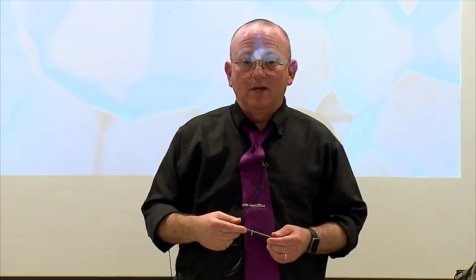That's what I'm saying. Now, imagine a system where there is no segregation, no equilibrium segregation. You have a dopant in solution, and it doesn't reduce the grain boundary energy, so it won't go there. And you go down to the length scales that you're talking about. Well, then we're talking about another thermodynamic parameter, which of course can shift the line of coexistence. And so the answer is obviously yes. But there are two different phenomena. And I address that because I've had problems of late with people assigning excess at boundaries as being part of the solute. And it's, of course, in balance with how much is in solution. But it's not related to the solubility limit.